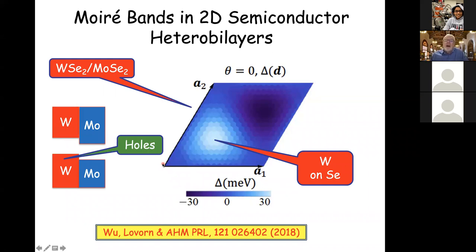They're actually described by a model of electrons with an effective mass that move in a periodic potential. It turns out there are only, in this material, two states with opposite spin at the top of the valence band. So this system actually, it turns out, maps exactly to free electrons with an effective mass moving in a two-dimensional periodic potential. And the period in space of that potential is the period of the Moiré pattern. And we'll see why that's important.